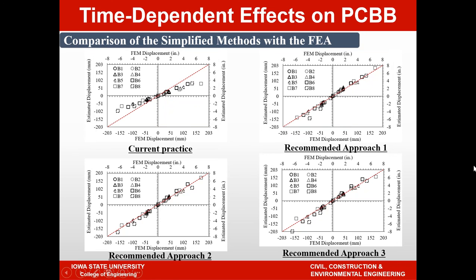Now, in this figure, we are comparing the estimated displacement of the columns using the three simplified approaches that we have done along with what we call the current practice, which is the one we are evaluating right now with Caltrans. But if you focus on approaches 1, 2, and 3, as I said before, you should expect good results coming from approach 2 because we are relying on the analysis outcomes from the finite element for each of the bridges for simple design calculations. And there's no surprise that they came out to be good.